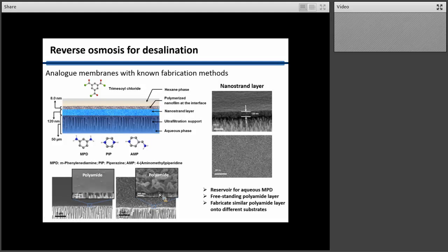And we think that's because as this interfacial reaction is happening, it's releasing heat. And that heat is creating instabilities and buoyancy effects at the interface, and those are essentially frozen at the time of the reaction when you form this interfacial film.